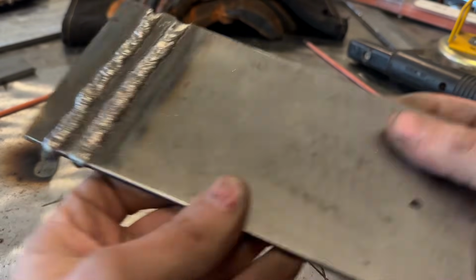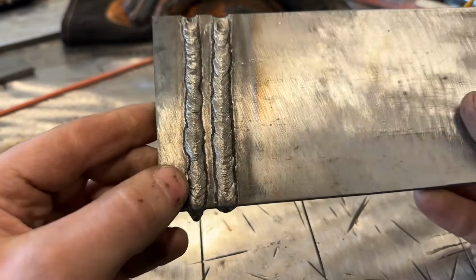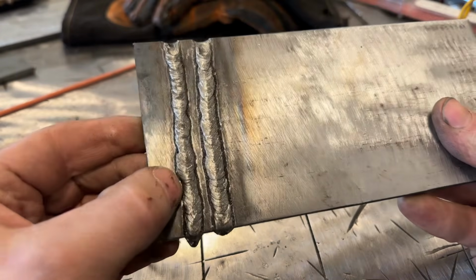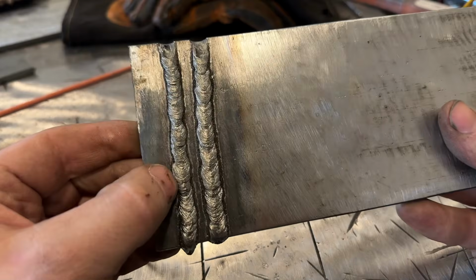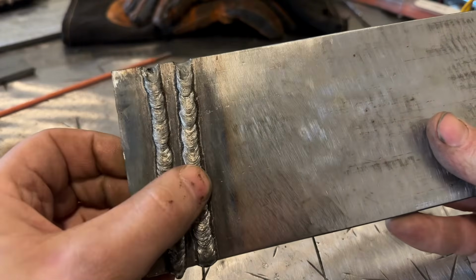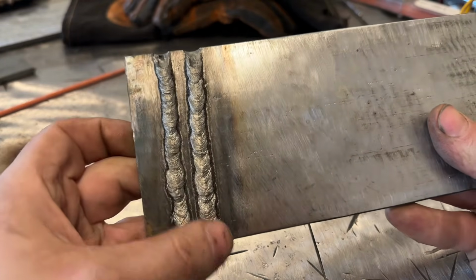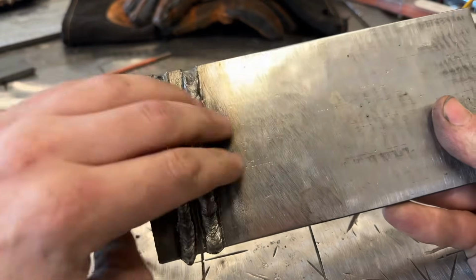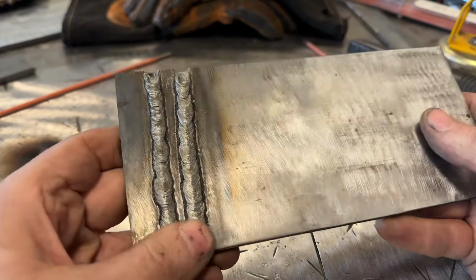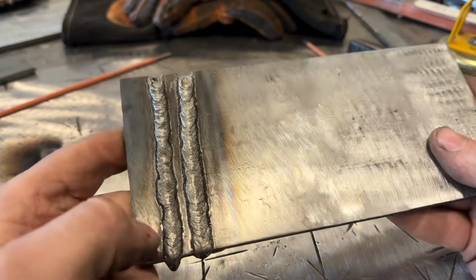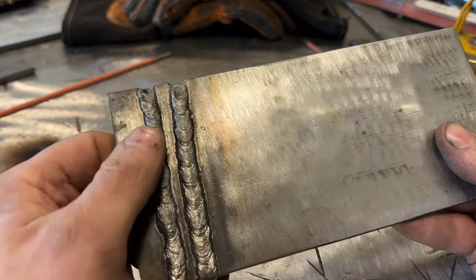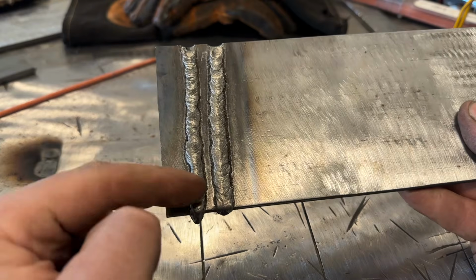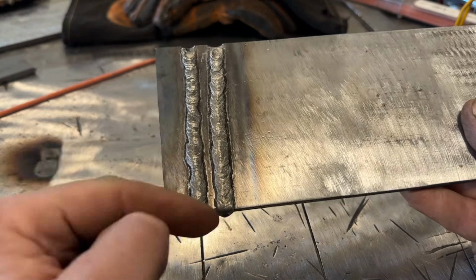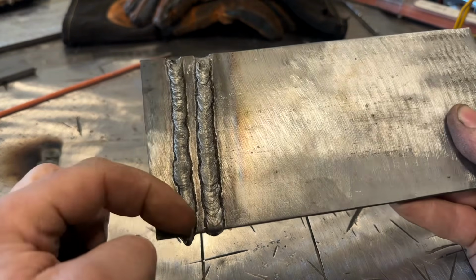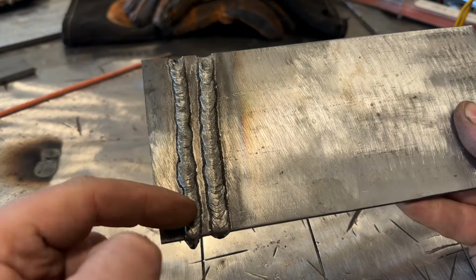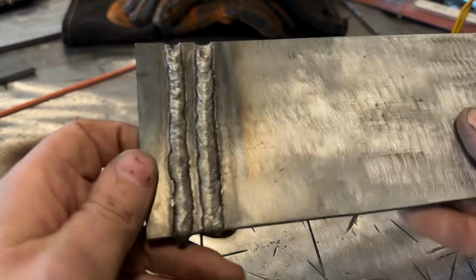Ran straight in. It still has not a stack of dimes appearance, but you can see where it narrowed down, got wider. My second pass was a lot better. That's partially due to the preheated plate allowed everything to flow out better, and partially I was just, I guess, smoother. It also helped that I had a reference point to weld to, because once I struck the arc down here, I couldn't see this edge and I didn't scribe a line, so I just went blind. Fortunately, the bead is straight, just not straight on the plate.